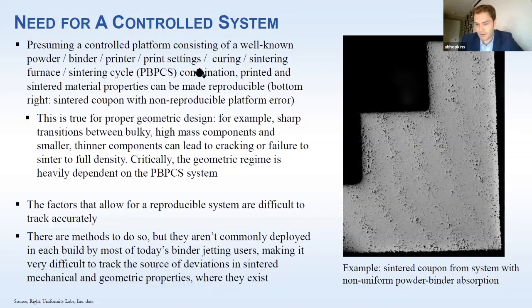Even in a repeatable system, this is something that went wrong. The powder surface chemistry was wrong. We did this on purpose to explain what it was. And therefore, you got bad layering of dry powder on top of bound powder. And you didn't get as much dry powder down on top of the bound powder. And you can see how the recoater was moving right to left. You can see how it's sort of pushing these wave patterns. And then when you sinter this, that's not a part you'd be happy with typically.